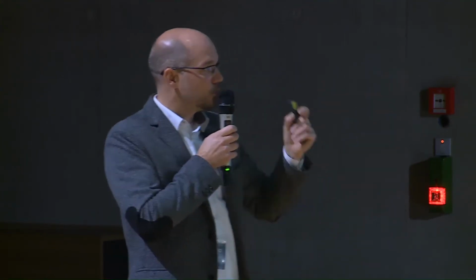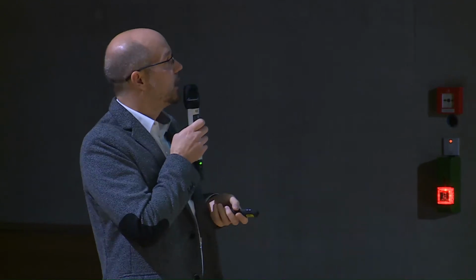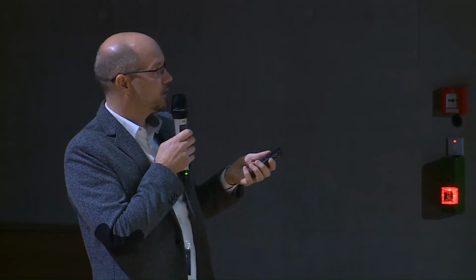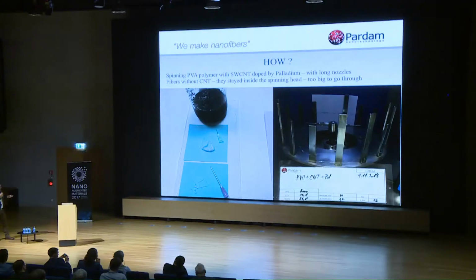of two different diameters, and what we have experienced is very low fiber production and very low content of carbon nanotubes, because the carbon nanotubes with a length of 5 microns find it very difficult to go through the syringes, through the nozzles. So they actually clog the spinneret, and just the polymer went out of the spinning head.